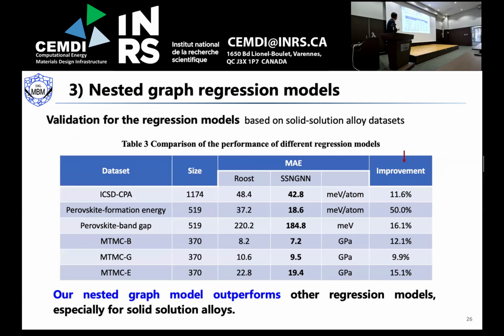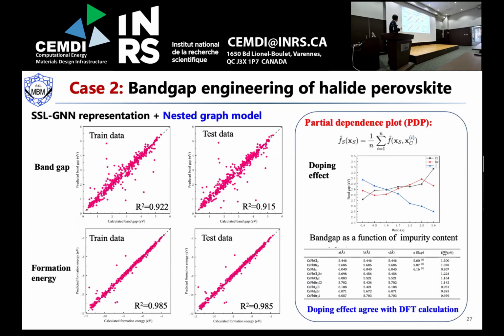We also do the benchmark for the solid solution data sets. These are well-known data sets, and we compare to the most well-known Roost method. And our method shows improvements for all the data sets. That means our nested graph model outperforms the Roost method, especially for the solid solution alloys. And we also did comparison for the band gap and formation energy for the training data set and the test data set. And based on this training model, we predict the doping effect. Once you add, I don't know, Cl, Br, and I into this kind of alloys, the energy changes.